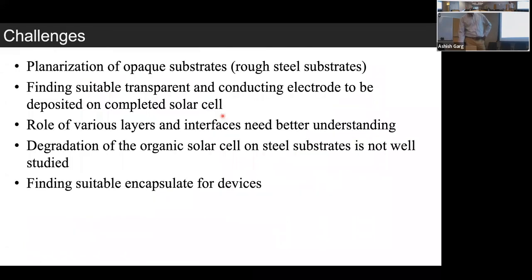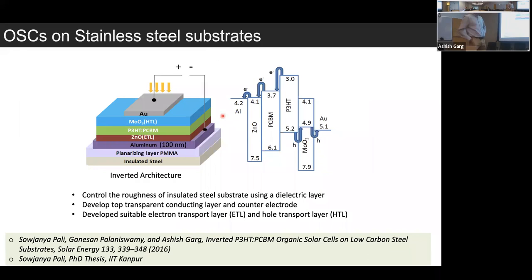So we did a literature review as to what kind of materials will have aligned bands. What we see is that if you use a steel substrate, you first have to planarize it using a polymeric layer, which in our case was a PMMA layer. Then we chose aluminum as a cheaper electrode, which could be coated easily on steel. Aluminum not only further planarizes the steel substrate, it also provides the N-type contact. Since aluminum is going to be the N-type contact, because the work function of aluminum is quite high, you cannot choose it as a hole collecting electrode.